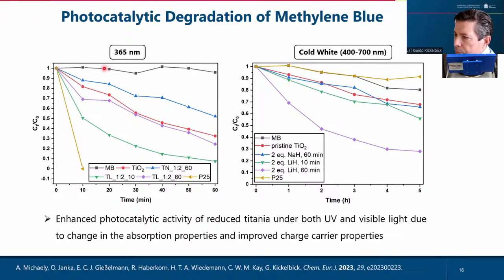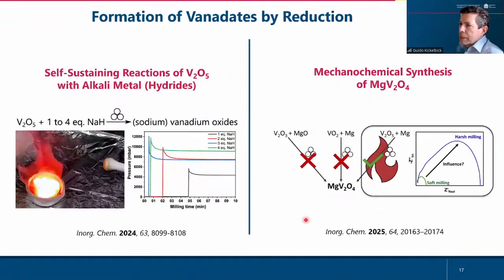In our case, the methylene blue with pure titania without any mechanochemical treatment is already not so bad, but it becomes better in the UV region for the mechanochemical treated systems. And in addition, also in the visible light region. Okay, so the question was now, can we do that also with other oxides? And here are some examples. You can look up the references here.